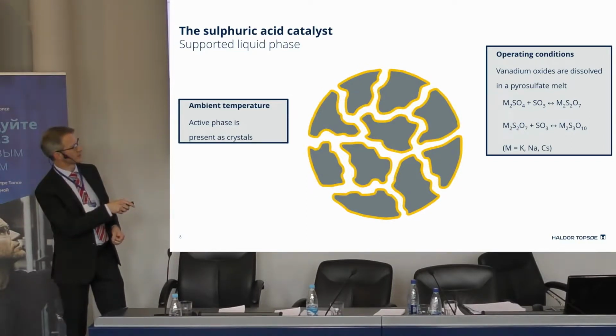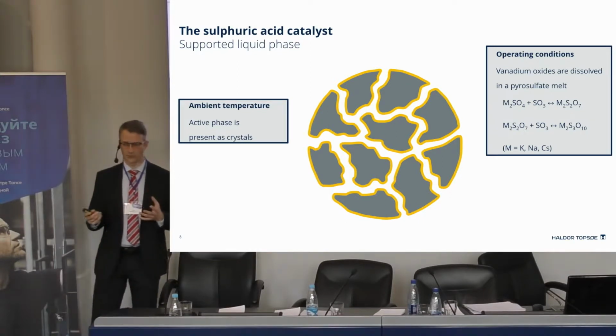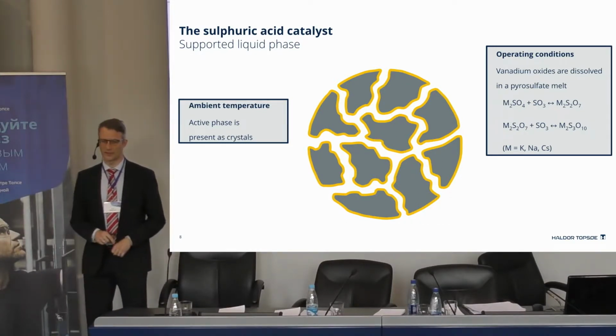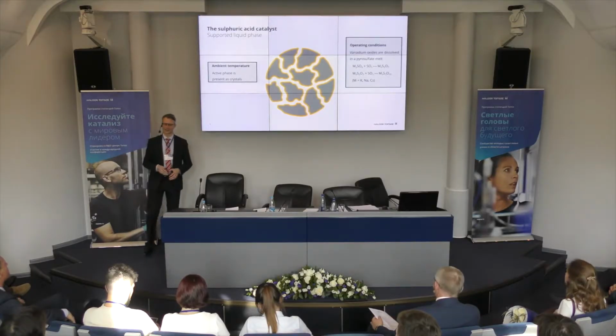So you can see the sulfates here of the alkali metals will take up SO3 to form pyrosulfate and dipyrosulfate. The pyrosulfate will melt and cover the catalyst surface, and the vanadium oxides will be dissolved in this melt. So actually, under operating conditions, about one third of the catalyst mass in a sulfuric acid converter is liquid. But the liquid is kept inside the catalyst pellets due to capillary forces.